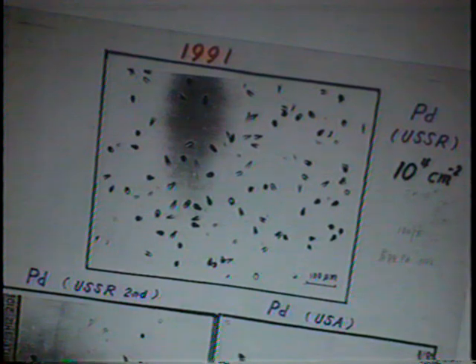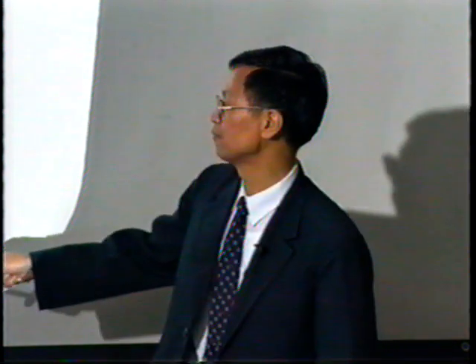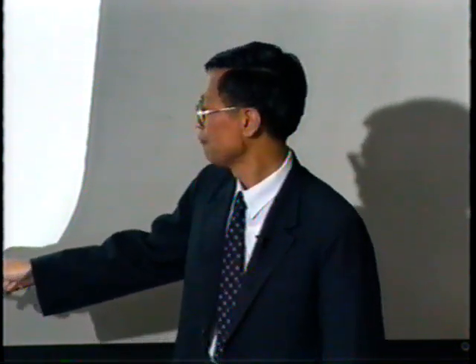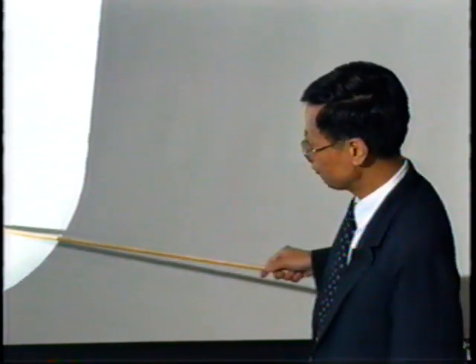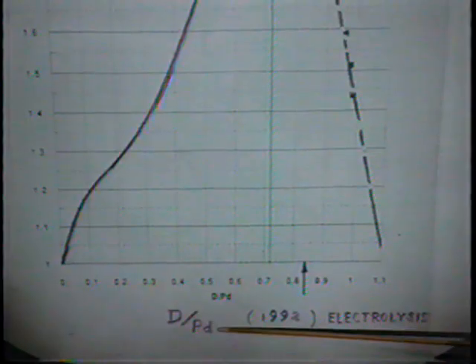If we can obtain something like this and frequently reproduce it, then it's worthwhile to study further. So we just switched our experiment to the loading ratio, because we believe the loading ratio is very important for this kind of reproducibility. I learned this from the Stanford Research Institute. This is the loading ratio, how much deuterium for each palladium.